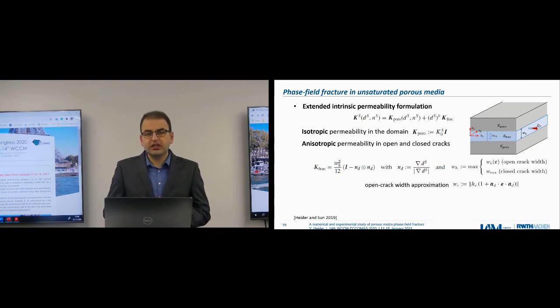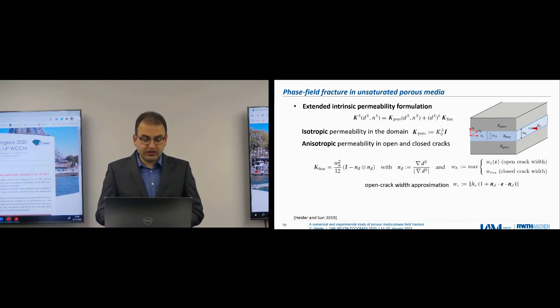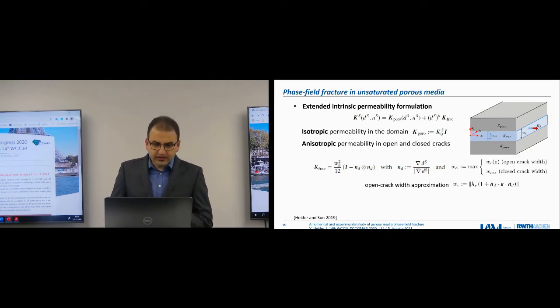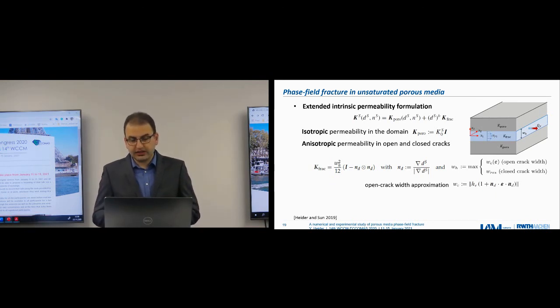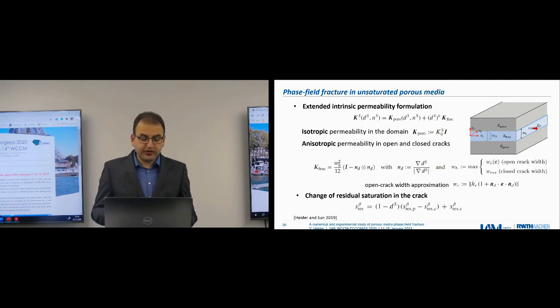When we have a crack opening, the flow in the crack direction will be enhanced. So we have a kind of anisotropic permeability, and this can be expressed in this relationship, which is written here. It's a function of WH, which is the crack width. This can also be determined based on the gradient of the phase field variable and also based on the local deformation of the material. So with this, we include in our model the isotropic and the anisotropic permeability. There are a number of additional extensions, like the residual saturation being different in the crack. In the cracks there will be almost no residual saturation, and this can also be considered in the model.